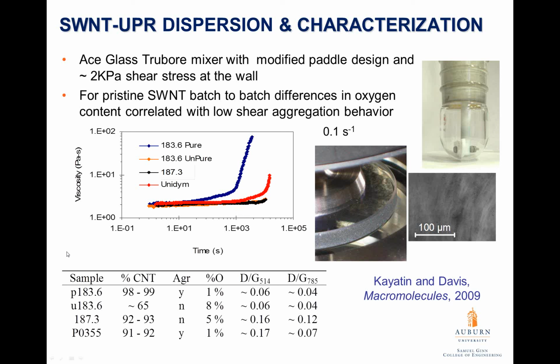We were able to correlate this to a more time-consuming and higher-tech method called X-ray photoelectron spectroscopy, which showed it came down to just a little bit different oxygen content from the purification scheme that was used. So we can use rheology, which is in line in many manufacturing plants, to look at these behaviors and develop better resins for these advanced manufacturing processes.